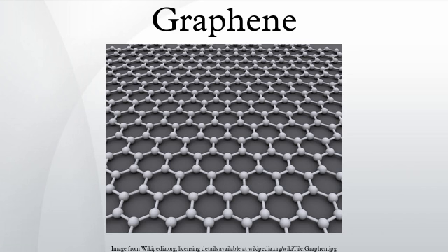The phenomenon is governed by the presence of elastic waves propagating in the graphene lattice, called phonons. The study of thermal conductivity in graphene may have important implications in graphene-based electronic devices. Even on a substrate, thermal conductivity reaches 600 W/m·K. Stability. Ab initio calculations show that a graphene sheet is thermodynamically unstable if its size is less than about 20 nm and becomes the most stable fullerene only for molecules larger than 24,000 atoms.